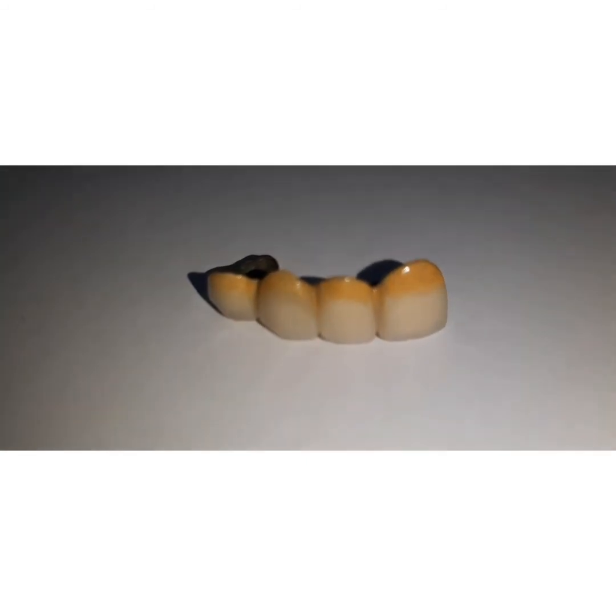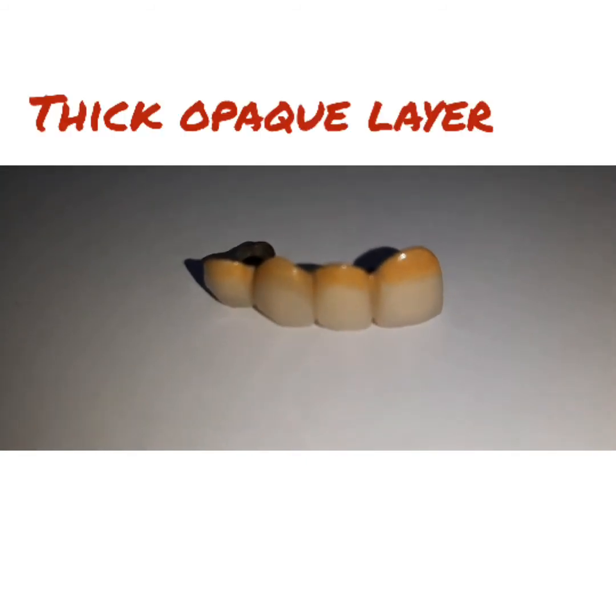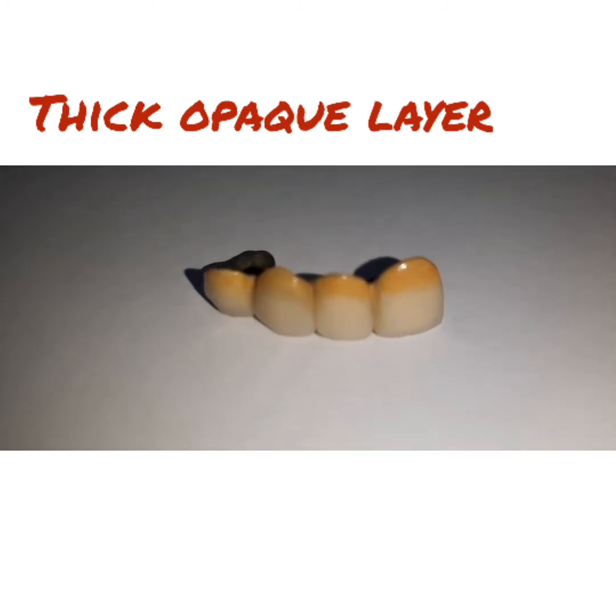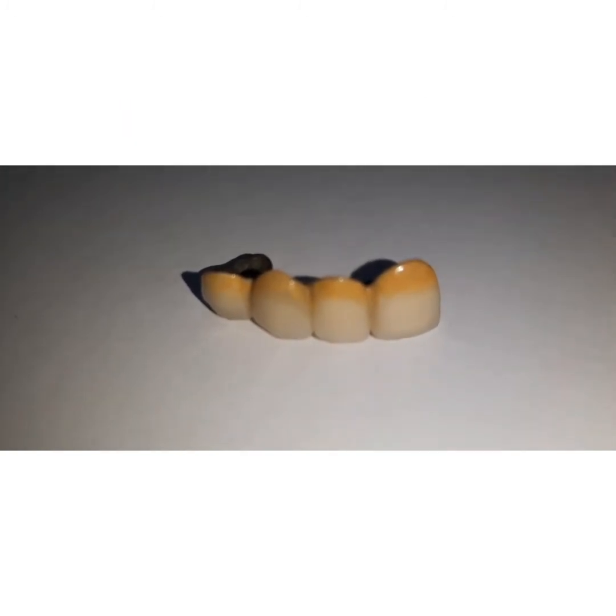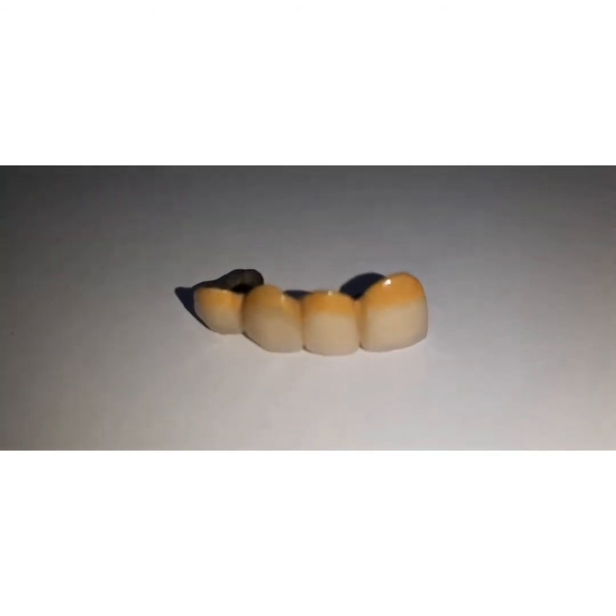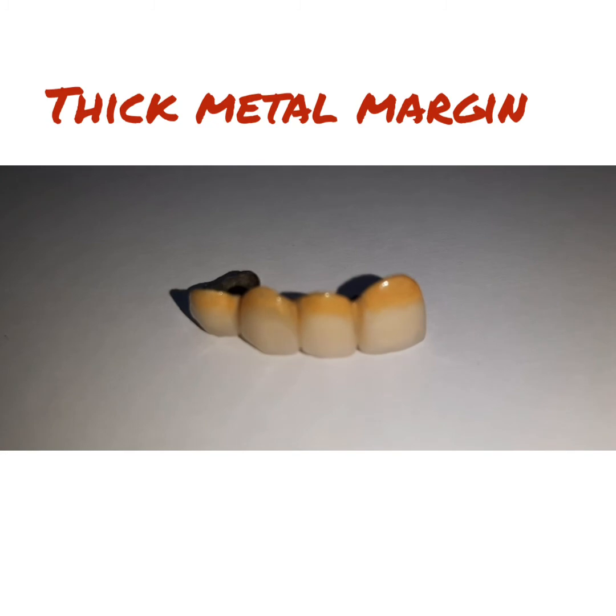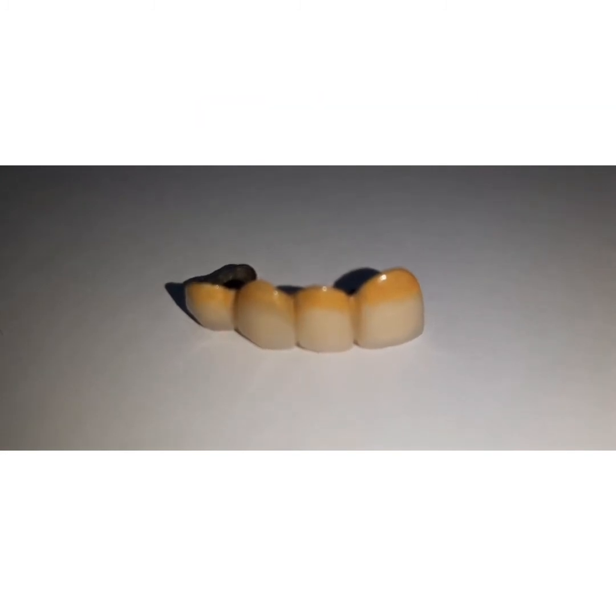The next type of aesthetic failure is an opaque layer that is too thick. If the opaque layer is too thick in your restoration, then definitely you will not get good translucency, and the tooth will not give a natural look. It will look more artificial, which the patient may not appreciate, and it may lead to failure of your restoration. Another type of aesthetic failure can be a thick metal margin at the incisal and the cervical region,